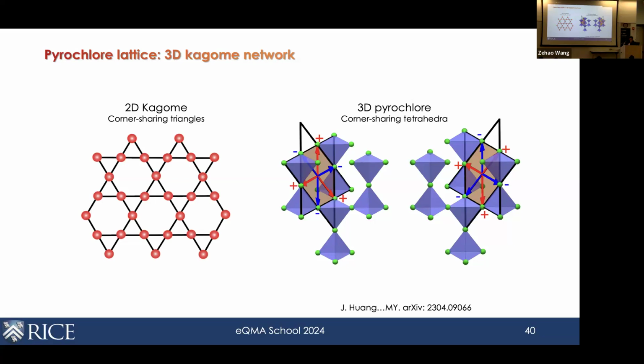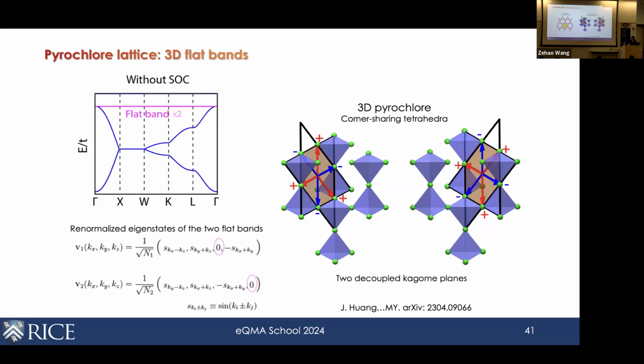And the destructive interference is actually still there in this 3D version. The way you can see this is that if we calculate the wavefunction amplitude on the 4 sites, the site which is not contained in the Kagome layer has 0 amplitude. Again, that means you cannot hop across the layers. And then here in the pyrochlore lattice, you have a three-dimensional quenching of the kinetic energy. So this should give you 3-dimensional flat bands. And indeed, if you do the tight binding calculation, considering only the nearest neighbor hopping, you get 2 copies of the flat bands and then 2 dispersive states. So this is the basic tight binding calculation for a pyrochlore lattice, which has been known in the field.